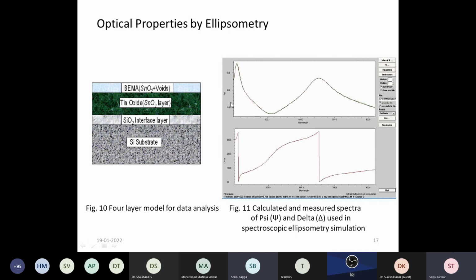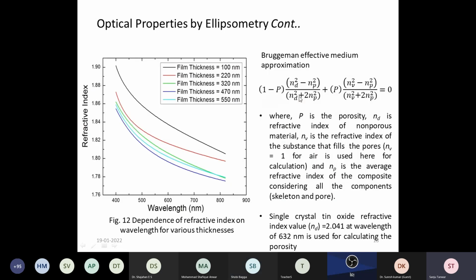For determining the optical properties, we have used ellipsometry. For that, a 4-layer model is used. Basically, we have taken a silicon substrate, a silicon oxide interface layer, then the tin oxide layer, and further we have used the Bruggeman approximation, so that the top layer consists of voids plus tin oxide, and we have simulated that. This is the psi and delta, which shows a perfect match. And this is the refractive index with wavelength. Here we can see the film of approximately 470 nanometer is giving the lowest value of the refractive index.